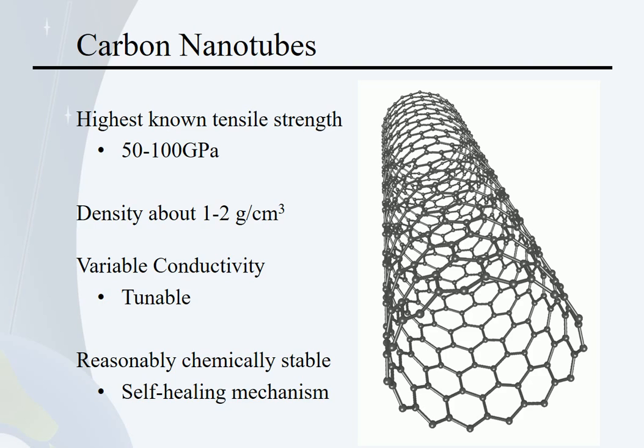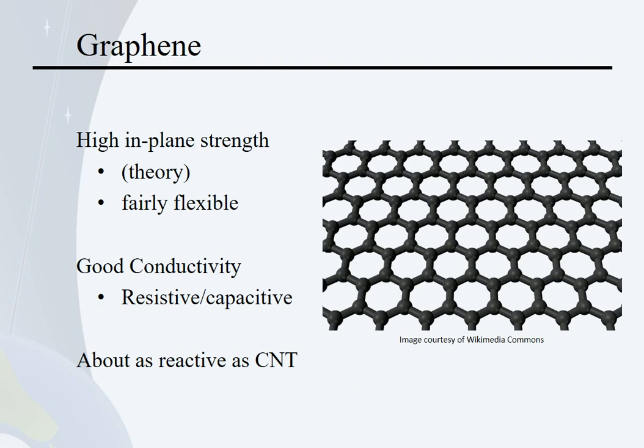With nanotubes, we don't have that. Oxidation just means damage and mass loss. It does not hinder further oxidation. So while it takes an aggressive environment to cause that oxidation to happen, once it starts, unless the environmental conditions change, it won't stop. If we're talking about carbon nanotubes, we also need to talk about graphene.